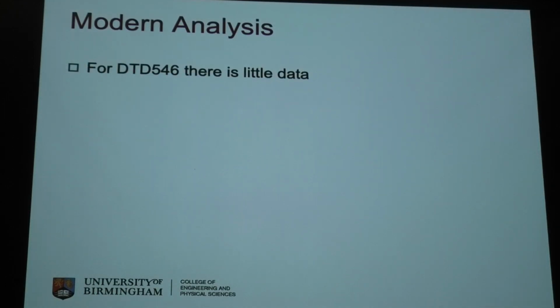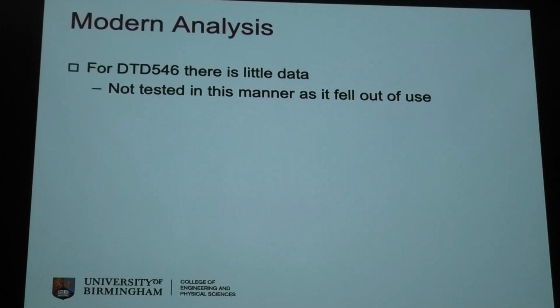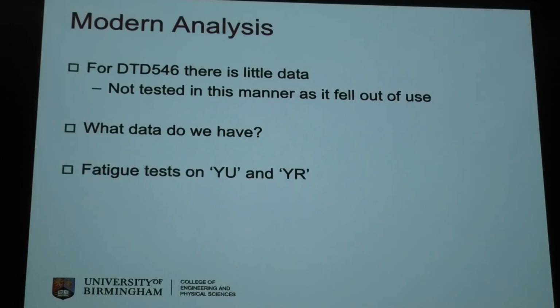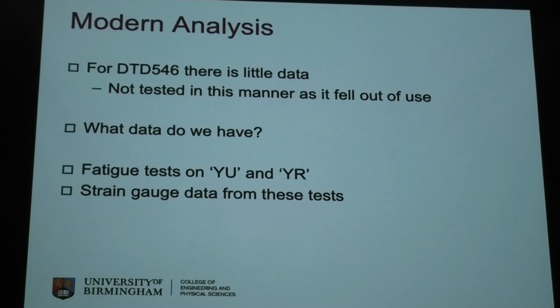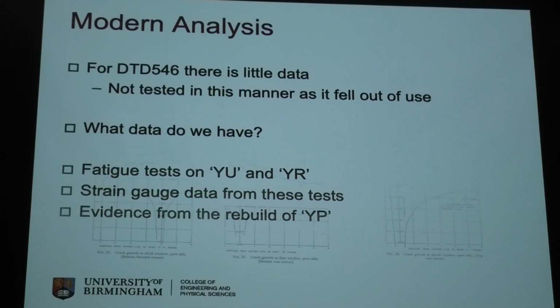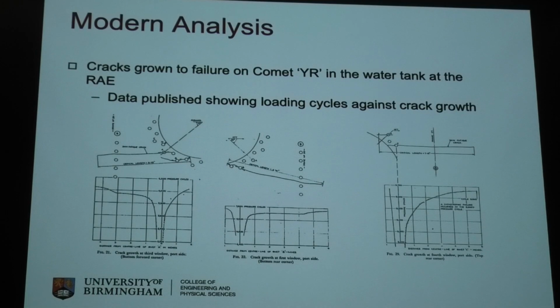But for the aluminium alloy that the Comet was made of, there's no data, really. We didn't test it in that way. It fell out of service, no use. So not tested. So what data do we have? If we want to test that we were right, we've got the fatigue tests on the frames, Yoke Uncle, Yoke Robert, and strain gauge data that I've just shown you coming out from the windows, and evidence of cracks on Yoke Peter. And we take all that data, which has been published by the RAE,